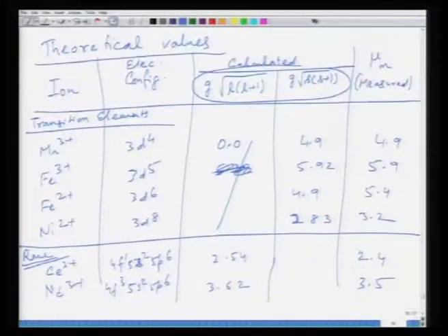Lastly, we looked at the quantum mechanical explanation, because quantum mechanics says that everything has to be quantized. So, moment also has to be quantized, and since moment has contributions from orbit and spin, in paramagnetic materials of interest such as transition metal elements, the magnetic moment per atom is spin dominated, whereas in the case of rare earth elements, since the orbitals are far off, they do not get quenched.